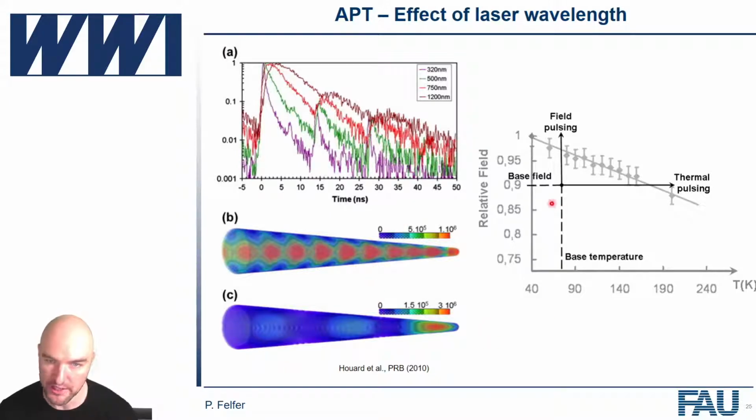But currently, on all regularly operating instruments, we are working with thermal pulsing. On the horizon, with extreme ultraviolet light, we have direct ionization processes, where we directly ionize, and we have athermal processes. This would be extremely important for us, because then we don't have all of those heating issues here, because the peak temperature also means that you can get diffusion on the surface. But for now, this is what we have.